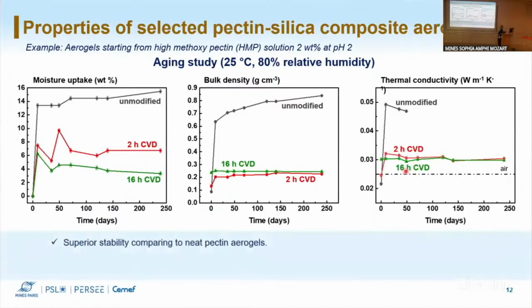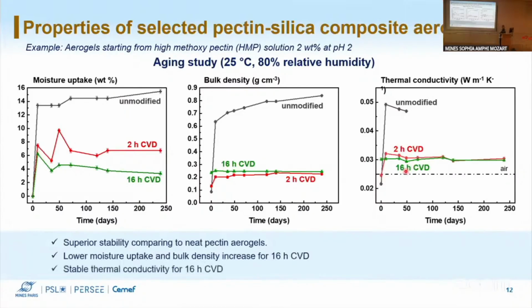So in general, we saw that for the composite materials, we have better stability, and we have lower moisture uptake and density increase when we have a longer deposition time. And for 16 hours chemical vapor deposition, we have stable thermal conductivity. However, we're not in the superinsulating area.